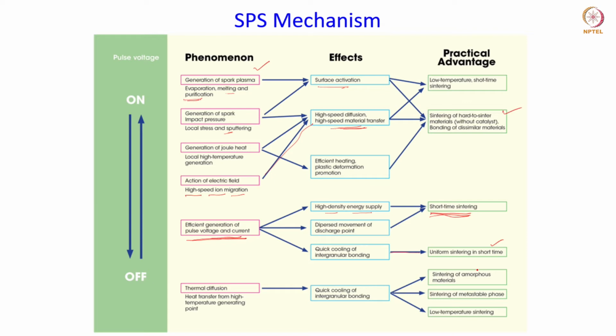And the practical advantage of that, you can sinter amorphous material, sintering of metastable phase, and low temperature sintering. So this kind of material where you need to preserve a particular microstructure or a particular phase has to be cooled down quickly, so that there is not enough time for any phase transformation or any changes that can lead to a change in the microstructure or the structure of the material, right? So therefore a quick cooling is always helpful for this kind of amorphous materials or materials having metastable phases.